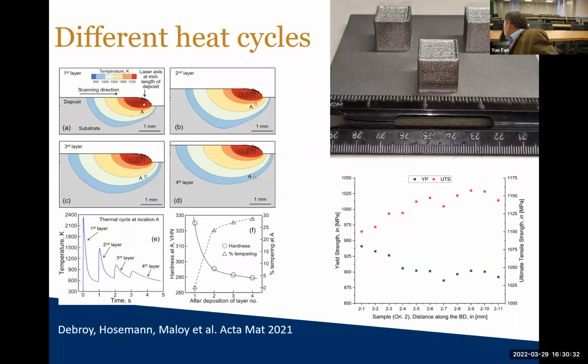What's interesting is, if you look at the top layer and the bottom layer, we see a very different yield stress. Ultimate tensile stress and yield stress change as a function of which layer we're looking at when you do tensile tests along the way. Again, the top one has only seen one heat treatment, maybe two, and the bottom ones have seen many, many heat treatments.